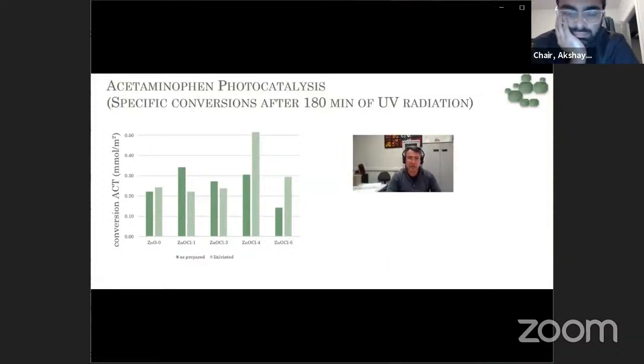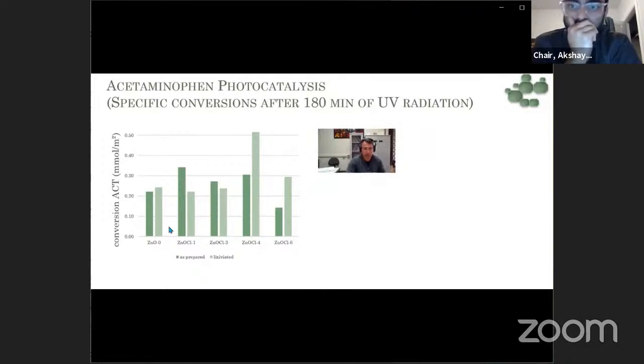We know that chlorine ions poison photocatalysts like ZnO. Therefore, when they are present on the surface, the reaction is reduced. However, after lixiviation, the reactivity increases very much, and mainly at the highest concentrations. And you see, for pure zinc oxide, we don't have any difference before and after lixiviation, but for high concentration of chlorides, we have a big difference.